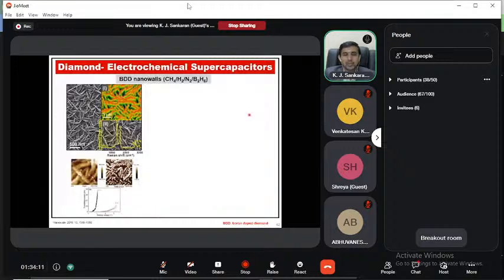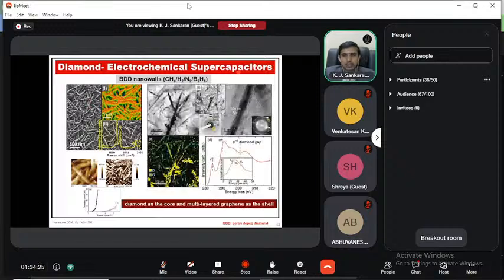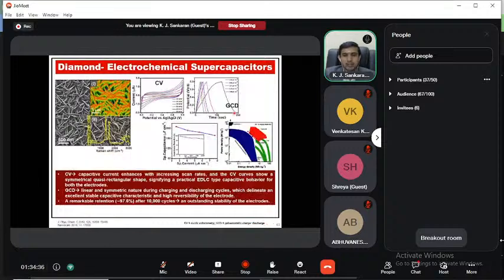What we have developed is that here also we have incorporated some nitrogen in the plasma. This creates a nitrogen and boron plasma that makes boron doped diamond nanowalls. You can see the one-dimensional nanowalls here, which show the presence of sp2 graphitic phases encasing the nanowalls, which is also a key factor in making a core and a shell. Diamond as the core and graphene as the shell makes a very good electrochemical supercapacitor.